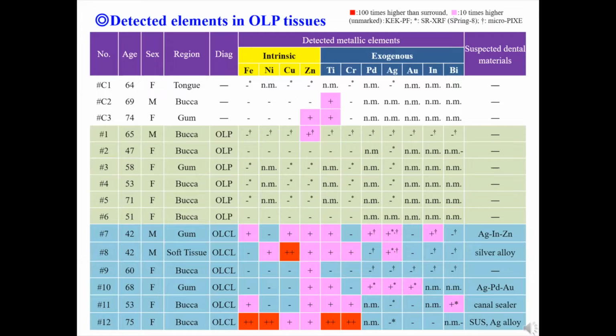We analyzed a total of 12 cases of OLP and the similar disease OLCL, and compared them to 3 healthy tissues. The effect of erosion of metallic restorations is strongly suspected for OLCL, oral lichenoid contact lesion. Some dental alloy elements were detected by XRF for OLCL. In contrast, metallic elements could not be detected for normal OLP and healthy mucosal tissues. Therefore, trace metallic element analysis by synchrotron radiation XRF could possibly be applied to the diagnosis of the causative materials of such mucosal diseases.